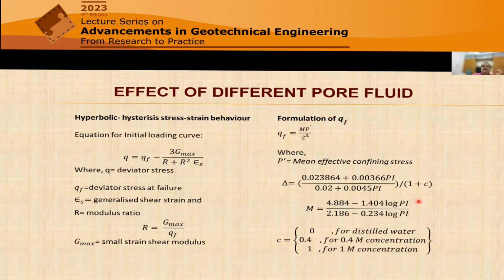And with that experimental behavior, we try to come up with a constitutive model for the contaminated soil with different pore fluids. What we have to do is simply improve the factor in the term called the concentration factor, and we have tested for 0, 0.4, 1 and others. And you see q equals M p' over 2 to the power delta; this is very similar to your typical critical state framework. Those who are working in critical state know that q, the failure strength, is M p' over 2 to the power n. With a similar idea, we use a delta, and that delta is a function of the concentration of these saturated solutions. And if we do that, we get a quite reasonable match.